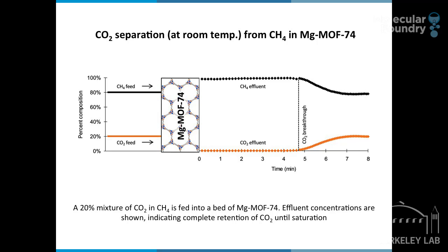Another very interesting application concerns the binding of carbon dioxide from flue gas or from combustion gases from power plants. This is a very important application for the environment, and I think MOFs figure prominently in the solution to that challenge. Here you see a mixture of gases, methane and CO2, passing through a magnesium MOF material. And you see on the other side, methane coming out in pure form, while CO2 is held within the pores. This is the kind of selectivity that is needed in order to make a change in the current carbon emission equation. And that is, can we use this technology? Can we further develop this technology so that we can capture carbon dioxide before it reaches the atmosphere?